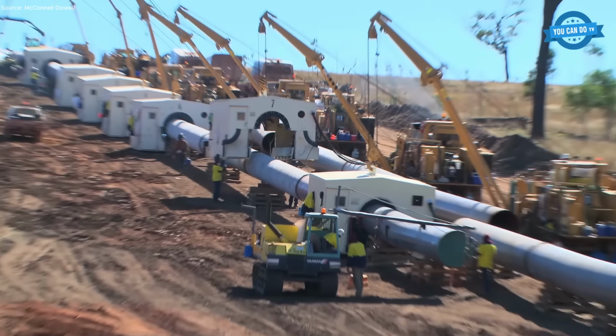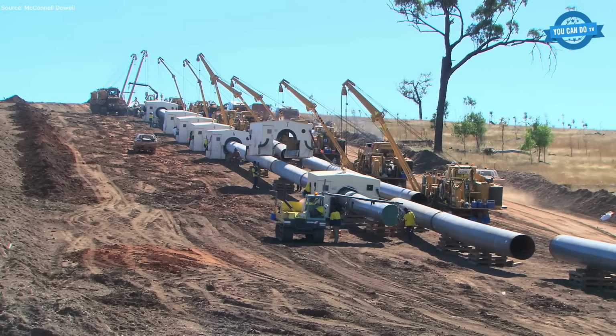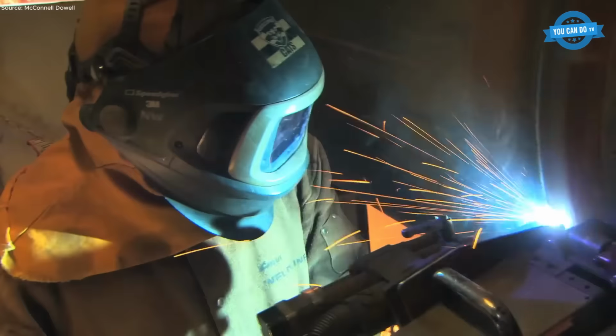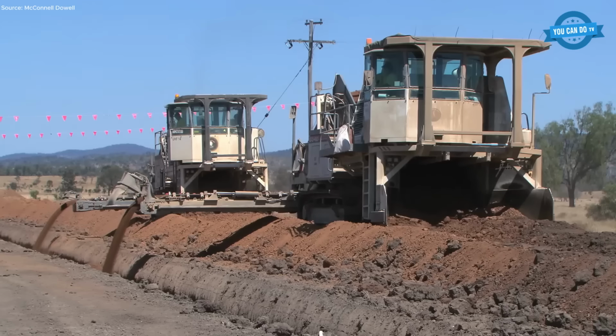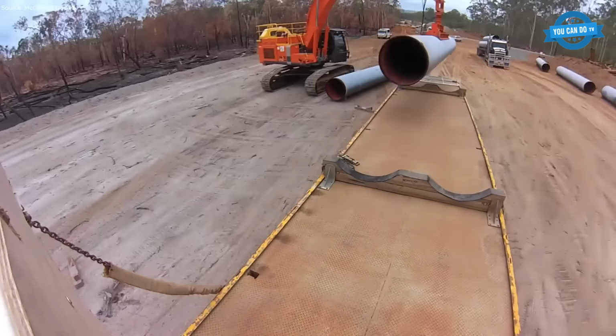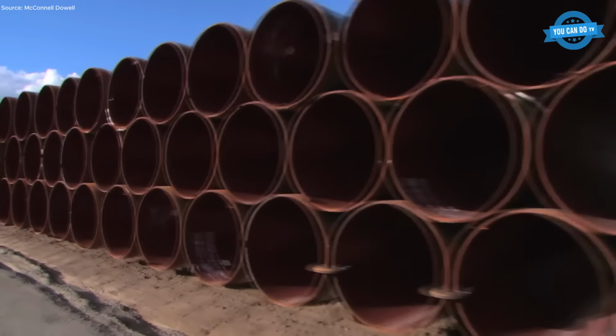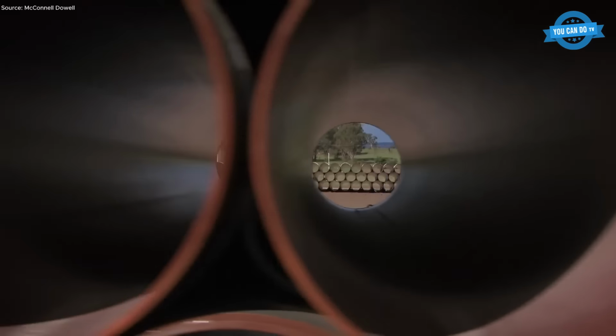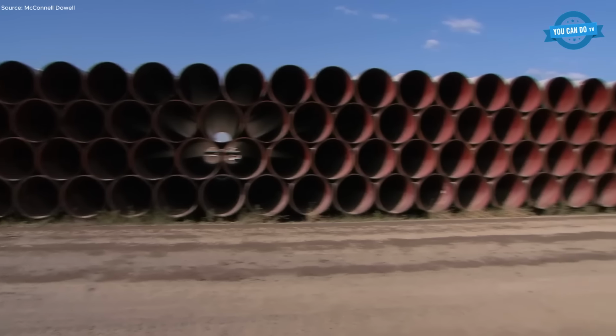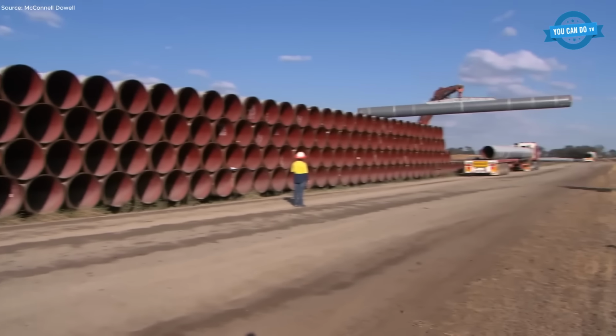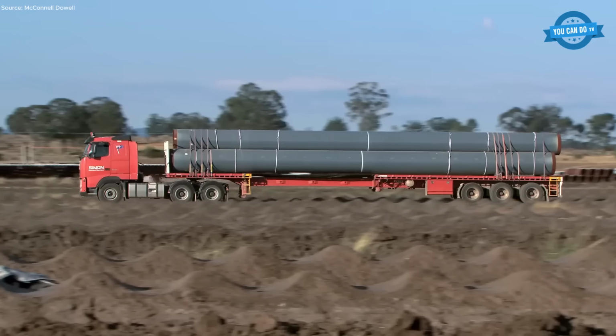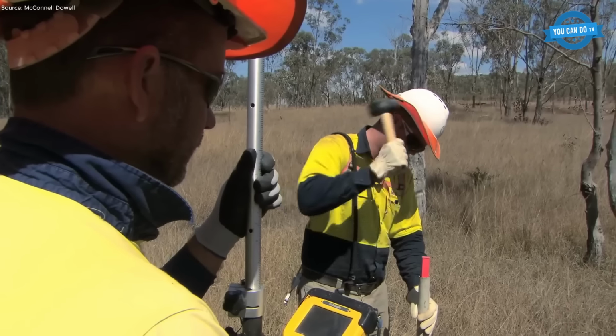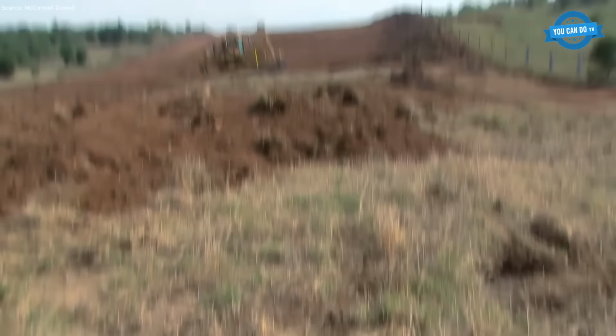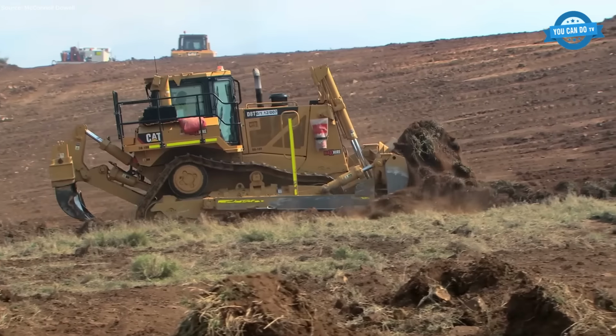A 40-meter construction right-of-way was established to support parallel operations, including trenching, stringing, welding, inspection, lowering in, and backfilling. 18-meter pipe joints were selected to minimize weld frequency, thereby improving productivity and reducing cumulative weld risk exposure. Automatic welding systems were deployed along a firing line configuration, achieving production rates of up to 150 girth welds per day.